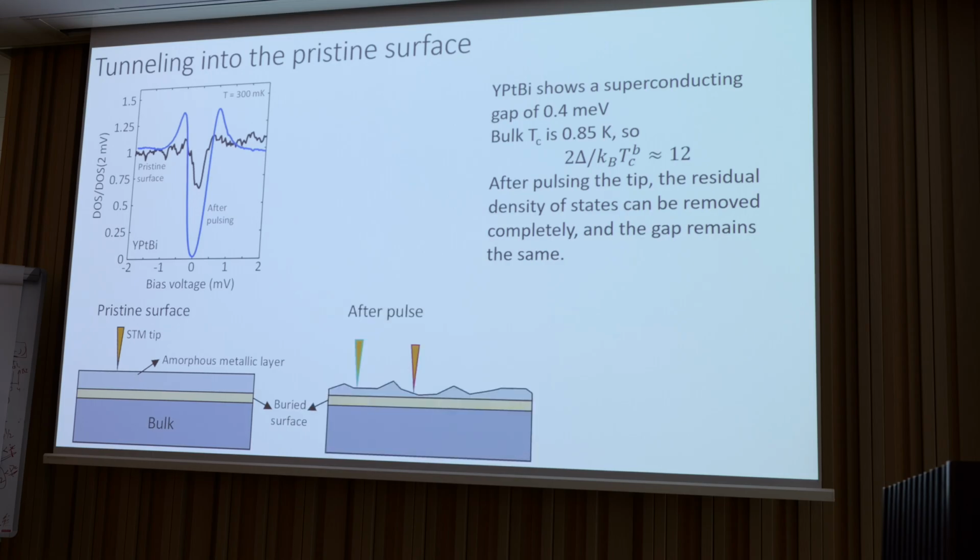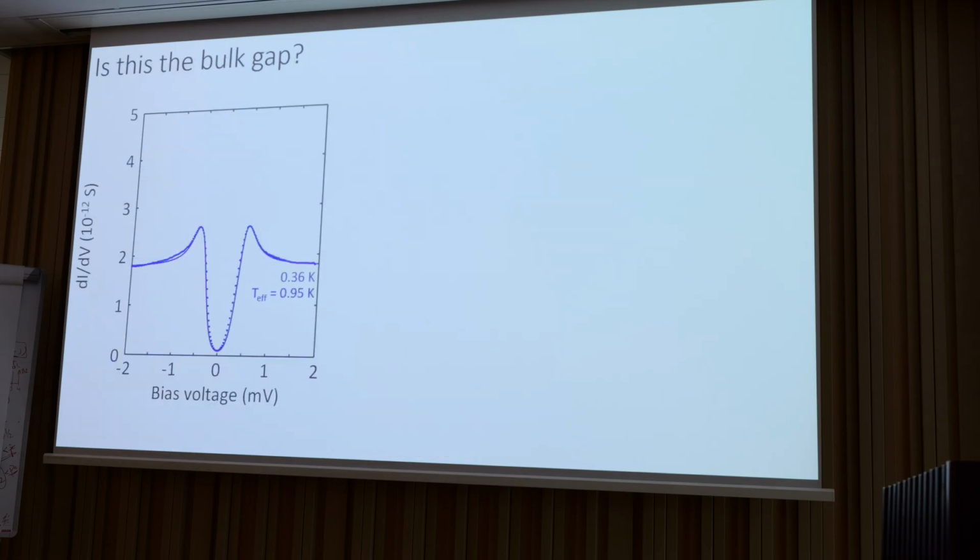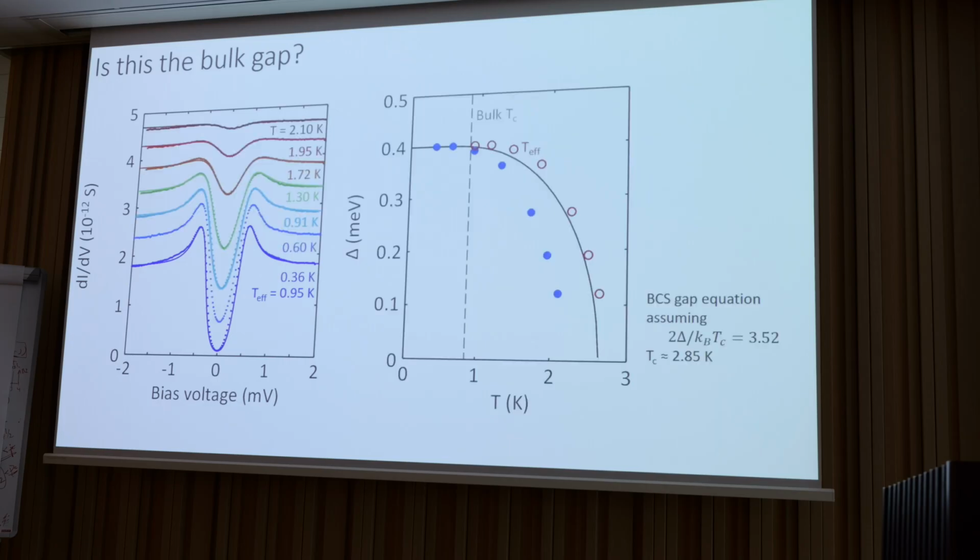And then what you get is this kind of a rugged surface where we've removed some of the junk. Now the tunneling can occur through a smaller barrier, so we can get really the superconducting, or the real surface of the material that we would want to study. We can take this data and fit it to a Dynes formula. We leave the temperature as a free parameter to account for electron heating. We can do this for various temperatures.